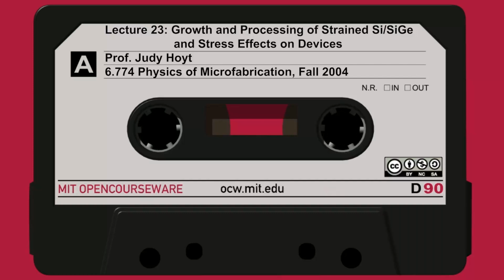So that's kind of a more well-characterized and well-known structure where the germanium fraction in a typical HBT you would buy off the shelf right now is probably between 10% and 20% of the atoms would be germanium in an HBT. On the other hand, if you grow the opposite structure, so you have relaxed silicon germanium substrate and you grow a thin layer of silicon, remember we said this was biaxial tension, the band lineup is quite different. In fact, you do get a sizable difference in the conduction band position. And in fact, the conduction band is lower. The energy is lower in strained silicon, so the electrons will tend to go into the strained silicon layer.